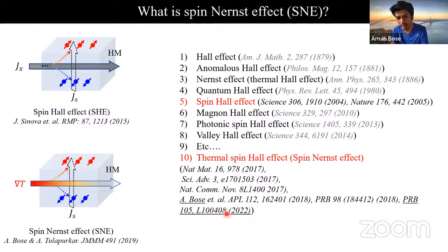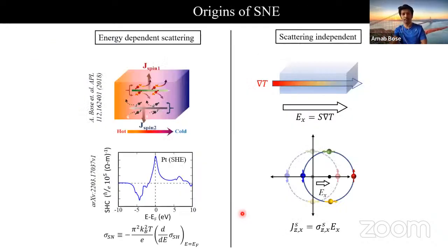So we have recently done some work, and I will explain our recent report in this context. Now the question is, what could be the mechanisms? One of the mechanisms could be the energy derivative of spin dependent scattering. Meaning even if there is no net flow of charge current when we apply the thermal gradient, we can still imagine the flow of hot and cold electrons just above and below the Fermi energy level, but they are equal and opposite, resulting in a net current equal to 0. But they can still have different scattering, and finally it can lead to a resultant net spin current. Meaning, as predicted in a recent work, if we have energy derivatives of the regular spin Hall effect, we can get the thermal analog of it.